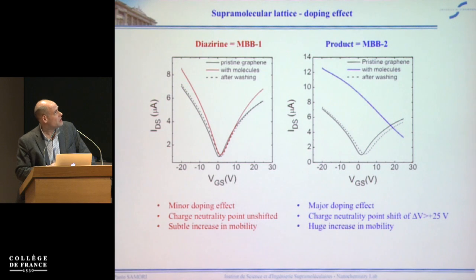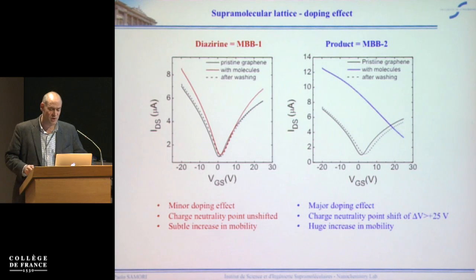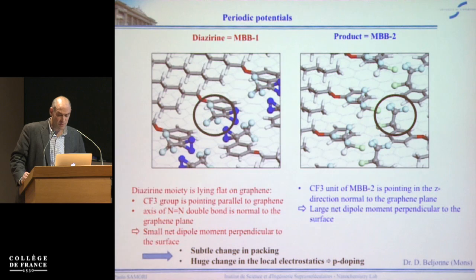You can notice here. When we do the same experiment, but this was done on MBB-2, you can see that there is a large shift of the neutrality point up to 25 volt, and there is a huge increase in mobility. So this is a major doping effect. And now, in what we are doing here, we are changing, let's say, the amplitude of our potential. And now, why is this? So this was the help we got from Mons doing modeling.